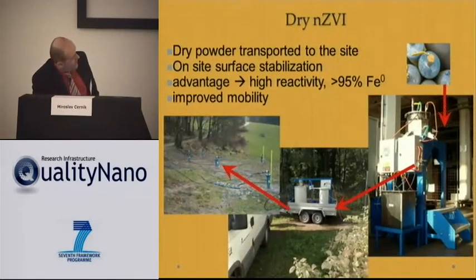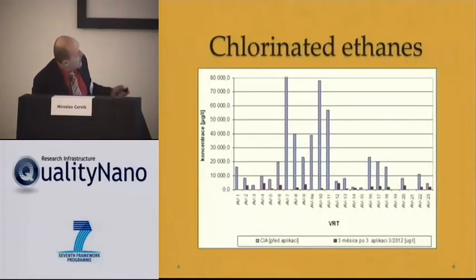Now first, how we do the application. We come with the powder particles. Then we do the dispersion on site, where we add some surface stabilizers to improve the particle migration, particle mobility, and then we apply some 1 or 2%, 2 grams per liter solution to the application well, and we do the monitoring. And the monitoring is shown as an example here. This is the concentration of chlorinated ethanes.